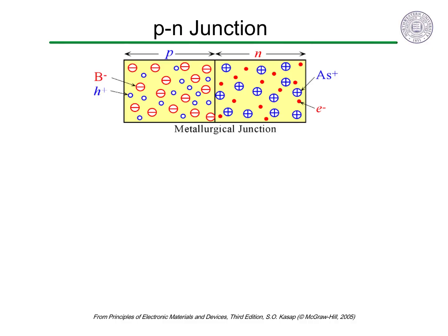Recall that normally a p-type material has free holes but is charge balanced by the ionized dopant atoms, here negatively charged boron atoms, that have localized an electron, creating a free hole. Similarly, on the n-type side, we have ionized arsenic atoms that have donated a free electron. With no net charge separation, there are no electric fields produced.